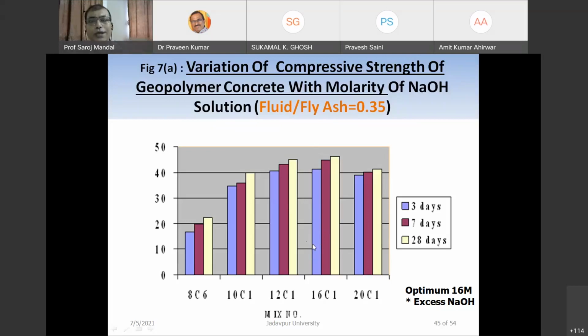If we add more alkali than this, naturally that alkali has no effect on that concrete. So that is your optimum. So 16 molar means we are getting the optimum hydration, optimum polymerization. For that particular mix, 16 molar is the optimum activation taking place. If we add more alkali, it has no use in the mix. That's why strength decreases.